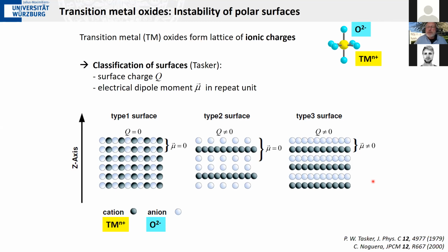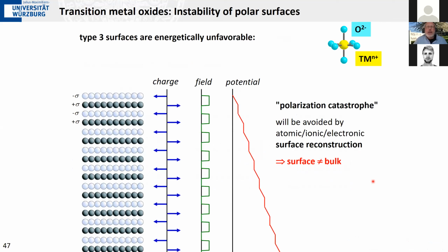And here you have a charged surface and a finite dipole moment. These have been categorized by Tasker, and there are nice review articles by Claudine Noguera on that. And this leads to surface reconstructions and surface changes with respect to the volume. This is due to the polarization catastrophe that most of you will know from LAO/STO, happening at the interface of lanthanum aluminate and strontium titanate. But of course, it also happens on the surface of such an ionic compound. If you look at the charge distribution in such a type 3 surface, look at the electrical fields and add them up to an electrostatic potential, you find that this is divergent as your sample becomes thicker and thicker. That's of course energetically unfavorable, and so the system will relax in some way, leading to atomic, ionic or electronic surface reconstructions, and then the surface will be very different from the volume.